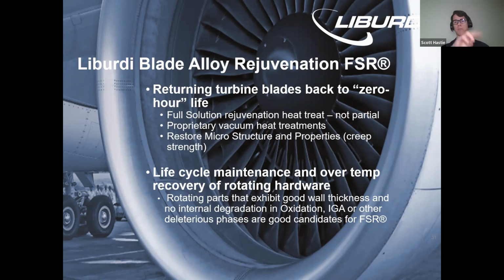We're taking that material above the solvus temperature and then holding it there for a period of time and then dropping it below, and then doing our proprietary aging heat treatments to develop the primary gamma prime and a secondary gamma prime structure, and that could be 1, 2, 3, or 4 additional heat treatments afterwards, after this full solution. And what we're trying to do is restore the microstructure and then therefore the creep properties, primarily the creep strength.